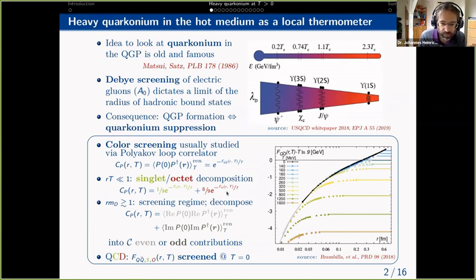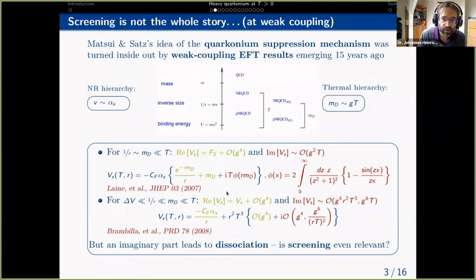Now, roughly 15 years ago, these ideas by Matsui and Satz were shaken up when complex potential results based on some EFT calculations emerged. We heard something from Peter already. The first calculation that was published was by Laine et al. It relied on the effective field theory called electrostatic QCD, where you assume that it's valid for inverse distance being of the order of the Debye mass, which is parametrically much, much smaller than the temperature.